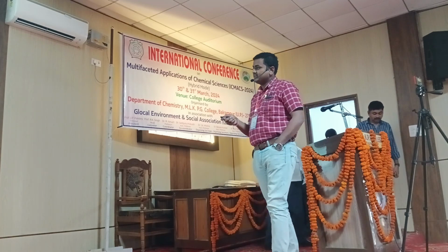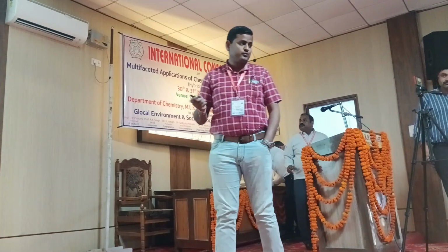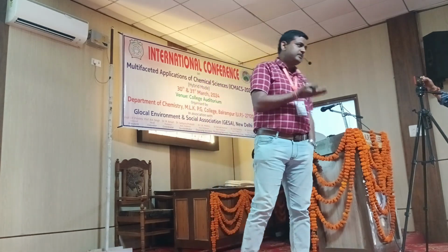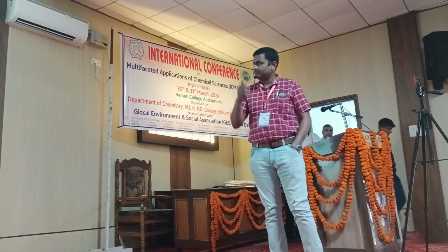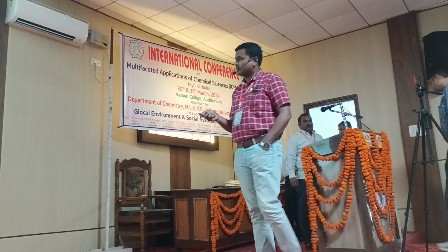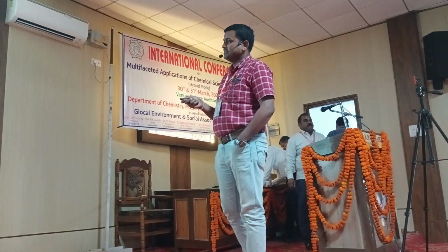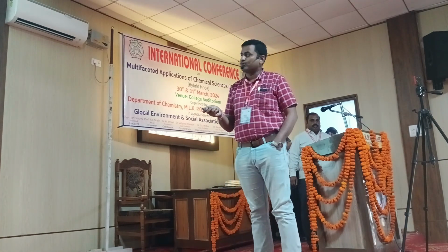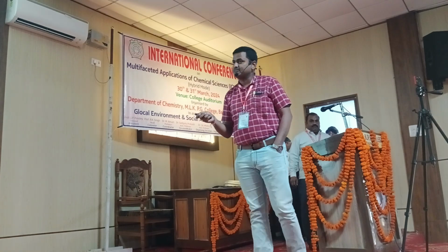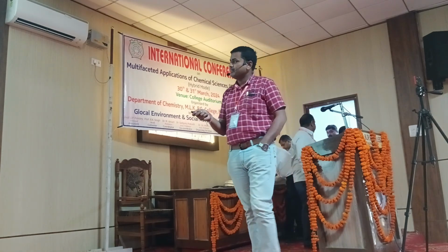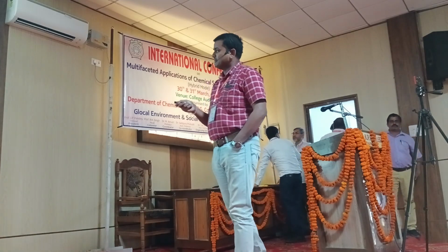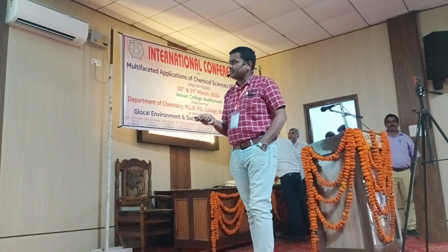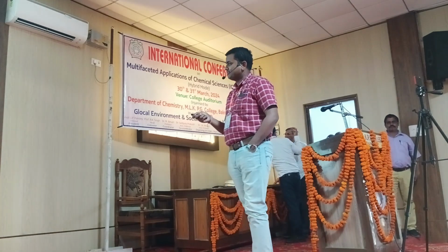So we have taken 1 milligram of coal soot, which we collected in our department from anthracite coal. We burned this coal and collected the coal soot on glass plates. Then we mixed this coal soot with 10 ml of ethylene diamine and ultrasonicated for 2 minutes at room temperature. We got the reaction mixture of ethylene diamine functionalized graphene quantum dots, and then we centrifuged this reaction mixture at 7000 rpm for 10 minutes. We have found the graphene quantum dots.